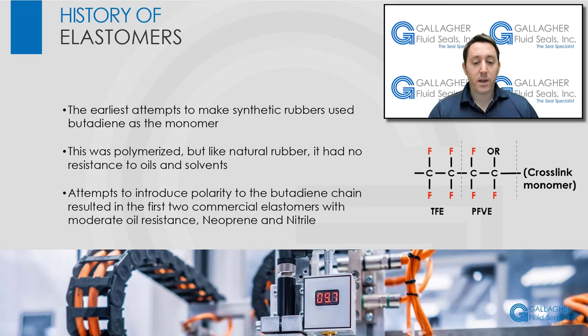This was achieved in the case of neoprene — polychloroprene — by chlorine addition. The added polarity in this case gave moderate oil resistance. The addition of acrylonitrile to butadiene as the copolymer gave the first truly oil-resistant elastomer. The higher the polar acrylonitrile content, the more oil or heat resistance was achieved with some sacrifice in low temperature properties. This elastomer was first produced as Buna-N, now known as nitrile or NBR.